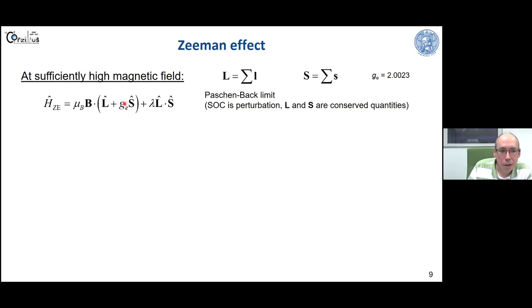So this true Zeeman effect, where this operator only acts on the pure spin wave functions, is always isotropic. However, as soon as we have a spin orbit coupling, this perturbs our wave functions, our eigenfunctions practically, of spin and orbital momentum. And this then starts to mix the two quantities together. And then we have to consider this at least in a perturbation treatment.